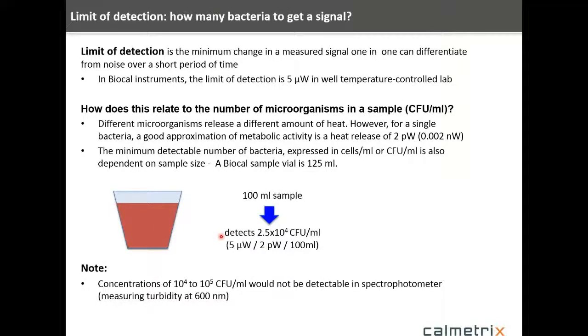And that compares very well with other techniques. For instance, it's a couple orders of magnitude better than what you might detect from, say, measuring turbidity. So it is a very sensitive technique. In many cases, you can sense the heat coming from the activity well before you can sense other parameters that you might measure.